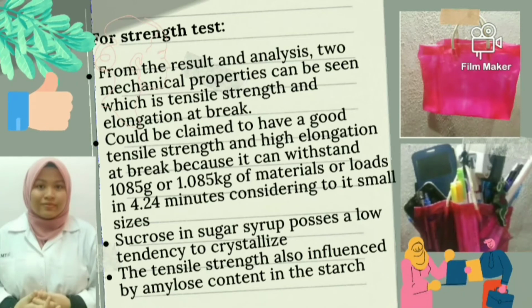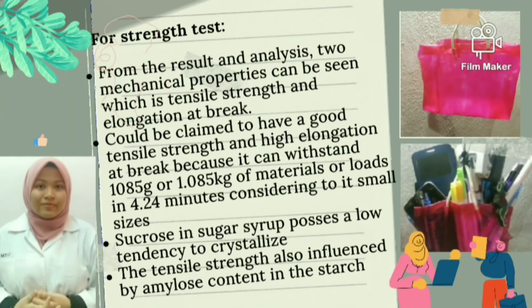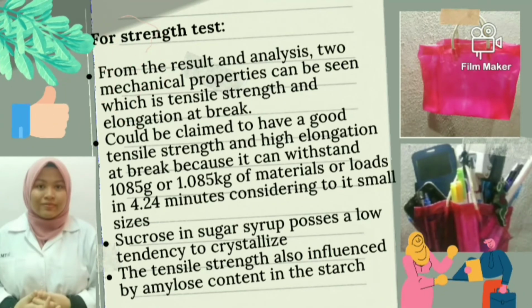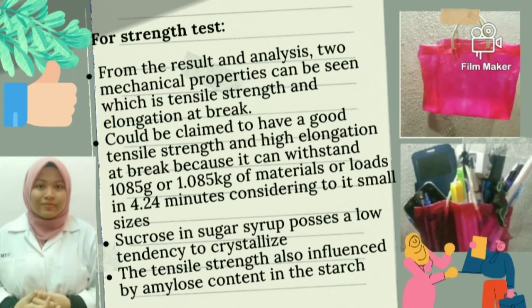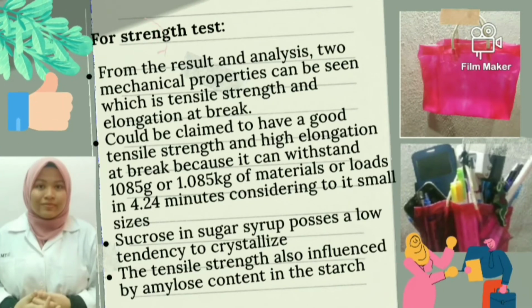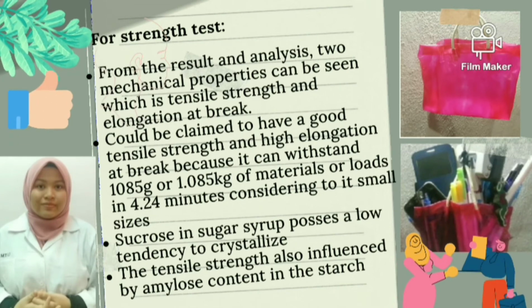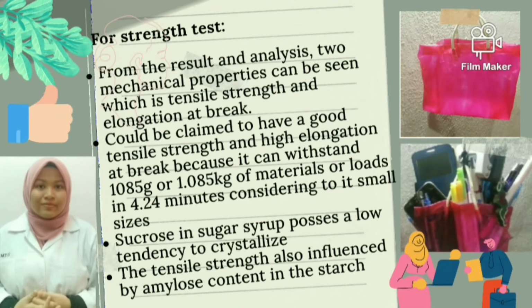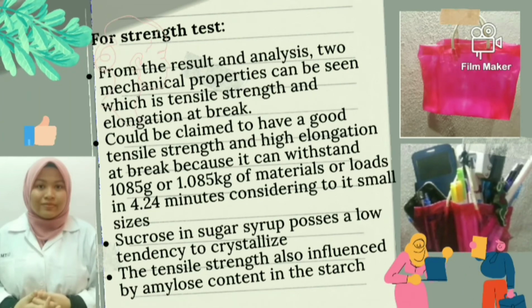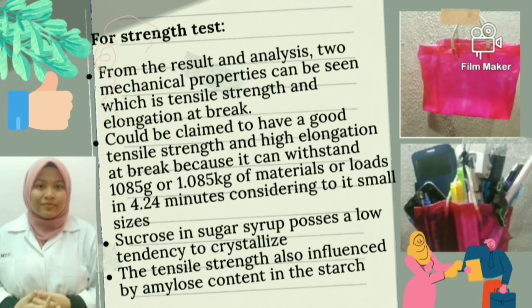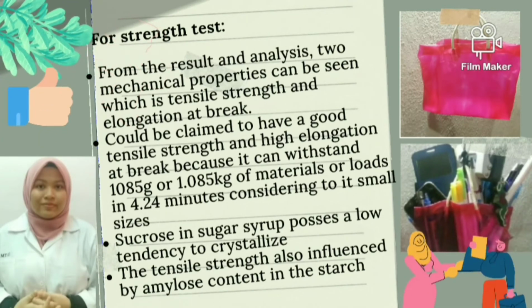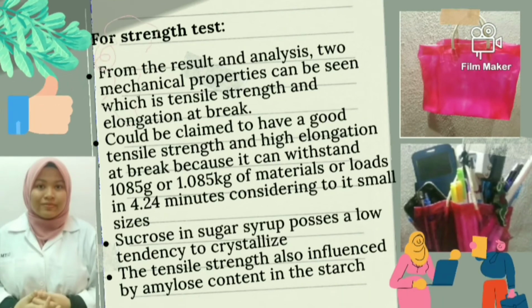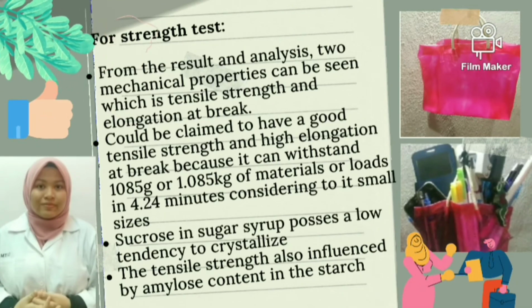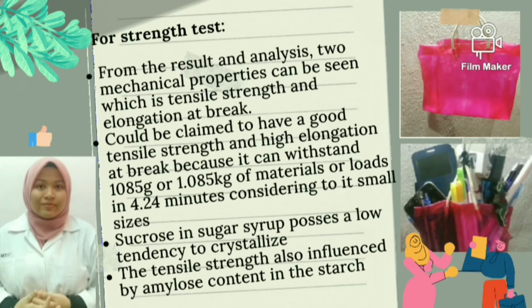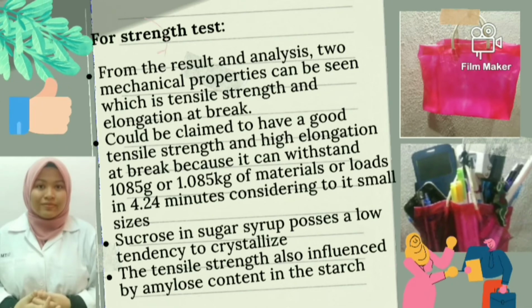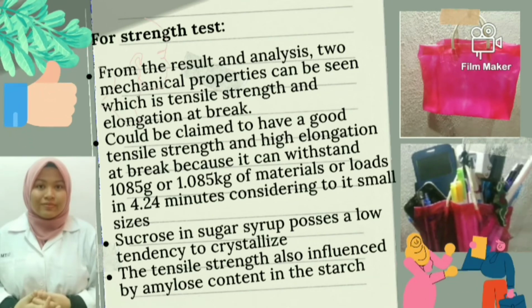Sucrose in sugar syrup possesses a low tendency to crystallize, so it decreases the breaking stress and increases the breaking strain immediately after preparation of the bioplastic. The tensile strength can be influenced by amylose content in starch, where when the amylose concentration increases, the tensile strength will also increase. Since we blend both corn and tapioca starch, the amylose concentration increases, so that is why our bioplastic has a good tensile strength.